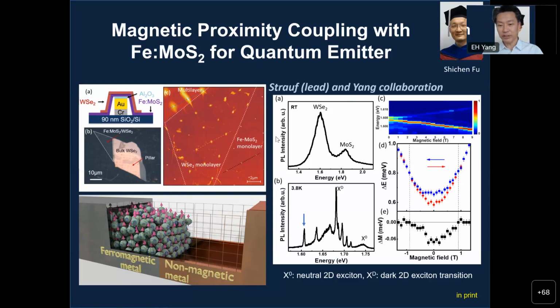What happens here is you can manipulate this delta E, where the peak splits into two. As you sweep the magnetic field, you can manipulate this quantum emitter using the magnetic field. In a way, it gives optical chirality to this quantum emitter if we use this iron doped molybdenum sulfide.